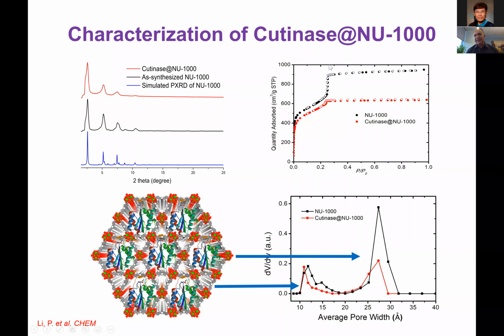You could see this step around 0.2 P over P naught, and that's a signature of a 3.2 nanometer channel. If it wasn't there, there is a problem. From this nitrogen isotherm, you could extract three pieces of information: surface area, pore volume, and pore size distribution.